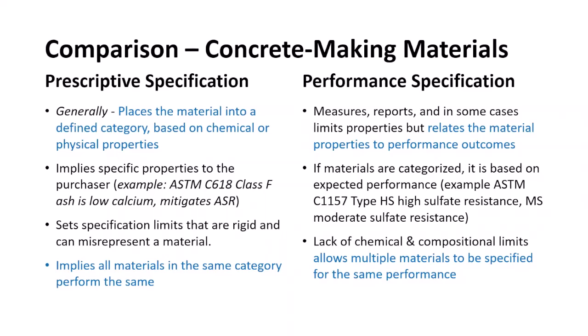Now, often they're a mix. If you look at ASTM C150, there's setting time requirements, strength requirements, but there's also compositional limits, for example. And it implies that all materials that meet those minimum limits in the standard are the same when they're prescriptive. So if we don't put the compositional limits in and we just specify performance, we can open up the doors a bit. We have a performance specification for hydraulic cements, C1157.